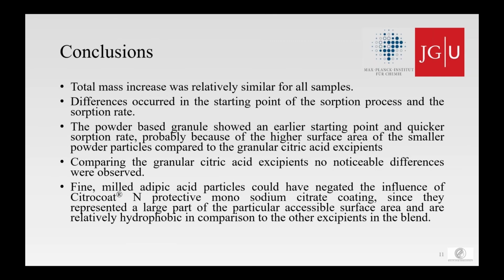So what did we get from these results? The total mass change was relatively similar for all samples. Differences occurred in the starting point of the sorption process. For the powder-based blends, it was at 55% relative humidity already, and for the granules at 60%. And also for the sorption rate, there were differences, the powder being the fastest, showing the fastest sorption, and the granules relatively similar and slower. One explanation for this would be that the powder, due to its smaller particle size, has a larger surface area, and thus the sorption process started earlier and also was faster compared to the granular excipients.